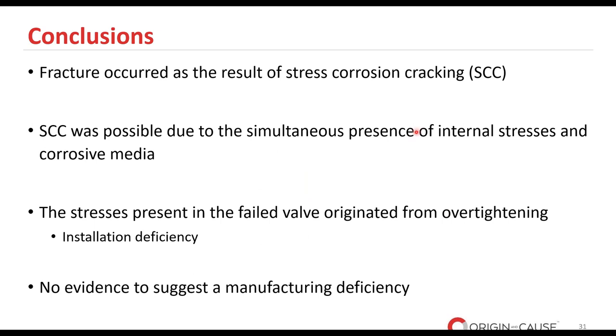To wrap up our investigation, the conclusions were unequivocal. The fracture resulted from stress corrosion cracking, or SCC. The onset of the stress corrosion cracking was facilitated by the simultaneous existence of internal stresses and a corrosive environment. Digging deeper into the stress source, the analysis identified over-tightening as the culprit here, which indicates an installation oversight. And most importantly, our examination found no grounds to attribute this failure to a manufacturing deficiency.